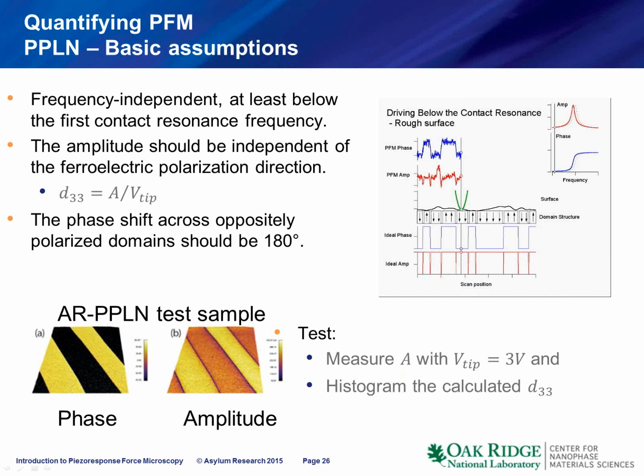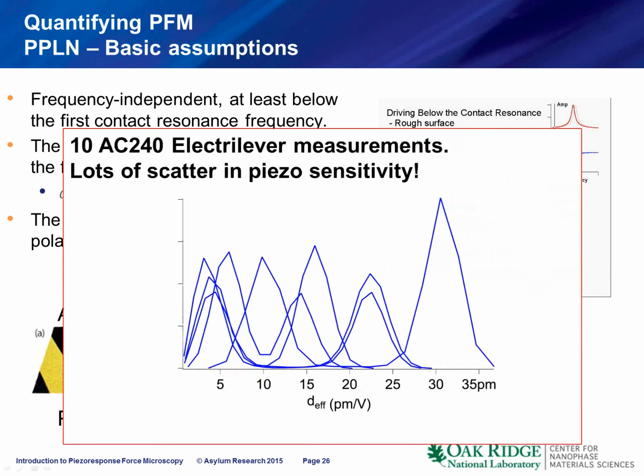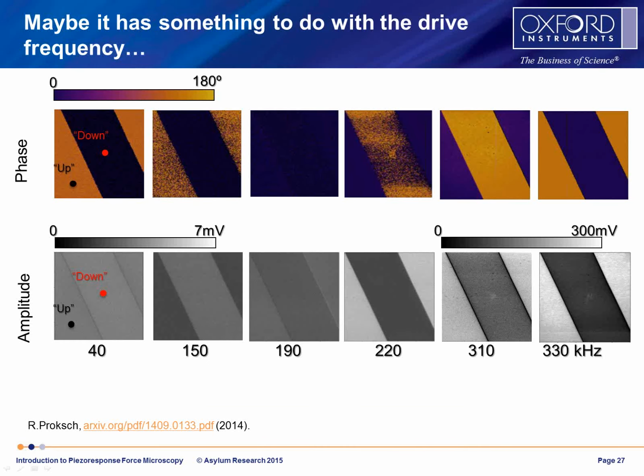The results were disappointing. The blue curve here shows the different histograms, and the estimated D33 ranges from a few picometers per volt to over 30, so quite a bit of scatter. We would like to have much better precision in our measurements. The question is, what is going on? Okay, so lots of scatter. What does that scatter come from?